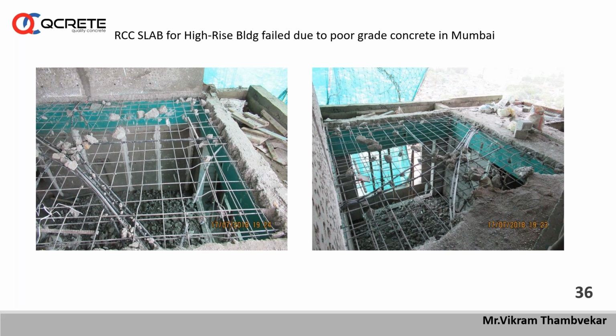He doesn't know which is the cement silo and which is the fly ash silo. He opens it, and says, put it here, put it there. Because of such a bad practice, such things are happening. And if a different material goes into different silos, then finally your mix design recipe goes wrong, and such problems may arise. So of course it is very necessary to take care to discharge the right material in the right silos.